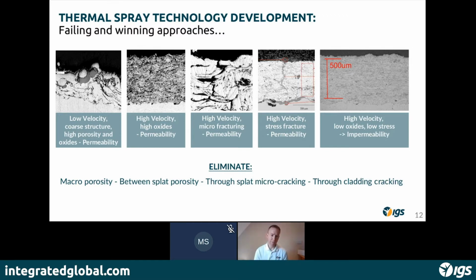And that's what led us to develop what we've been using since around 2000 and today, which is a high velocity process where we utilize a bespoke alloy to reduce the oxide content, reduce the internal stress, and make it applicable and robust to applications in the field. So this is the way that we get a corrosion-resistant alloy, a high nobility alloy, onto the internal surface of your equipment in order to resist the corrosive environment. And we provide this long-term protection.